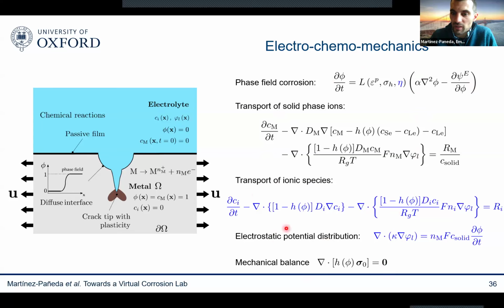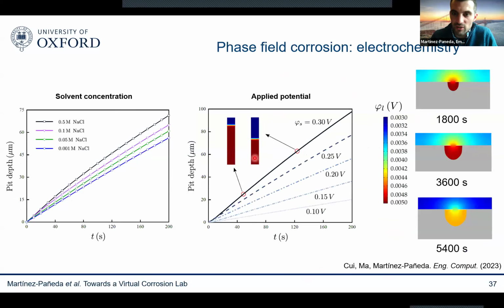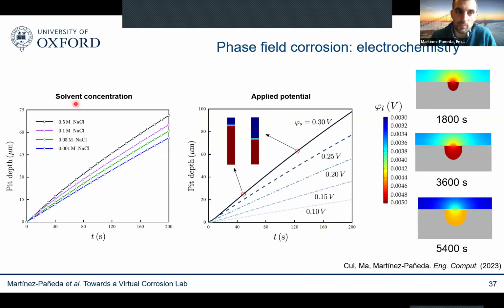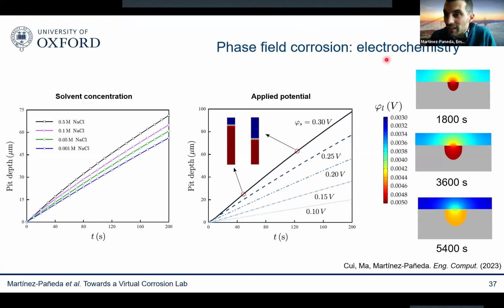So we can add the electrochemical behavior of the electrolyte and the Nernst-Planck equations. We can solve for the electrostatic potential distribution. We solve this for any relevant ionic species. We solve the chemical reactions, and then we can capture the role of the environment. So we can see, as we expect from experiments, how you change the solvent concentration, how it's going to change the pit depth. We can see the sensitivity to the applied potential, and we can see how the electrochemistry of the electrolyte is evolving as your corrosion pit or your corrosion front is evolving. You can capture that naturally. You don't need to make any assumptions on how much it changes and so on and so forth. You can see, depending on the pit geometry and the fluid flow and all the elements that are taking a role, how these things naturally evolve.